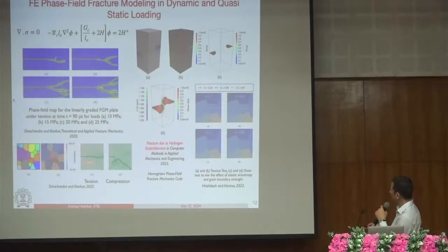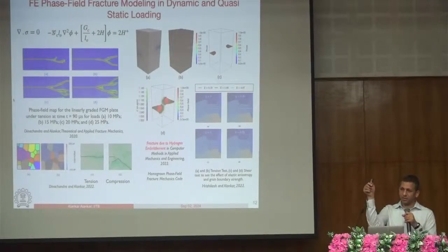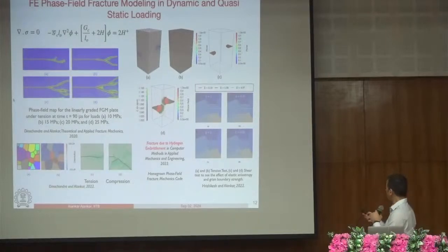This is a polycrystal fracture simulation. In this case, there is a tensile loading. This is a compressive loading. This is a finite element phase field fracture simulation for hydrogen embrittlement. The hydrogen is being introduced from the surface, and these are the initial cracks. As the hydrogen diffuses to the crack tip, the load is also being applied, and since crack tips are the most potential areas, they are the highest stress concentration areas. Hydrogen actually trickles to the crack tip first and makes the material brittle, and crack propagates even more.